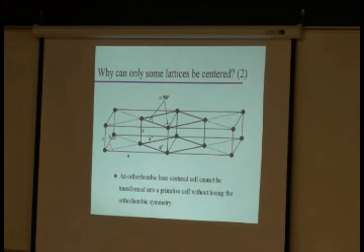And here's the example that we just looked at with the tetragonal cell, a base-centered orthorhombic cell. There's your brick. Okay, A, B, and C are all different lengths. And I drew it base-centered. If I do the same that I did for that last tetragonal cell, I again get a smaller unit cell, but these angles are no longer 90 degrees because the two unit cell axes were not identical. So, by definition, yes, we want the smallest cell, but of highest symmetry. In this case, choosing the slightly bigger cell will give you a higher symmetry. And so you choose that centered cell. Does that make sense to everybody? I see a lot of nods. That's good.